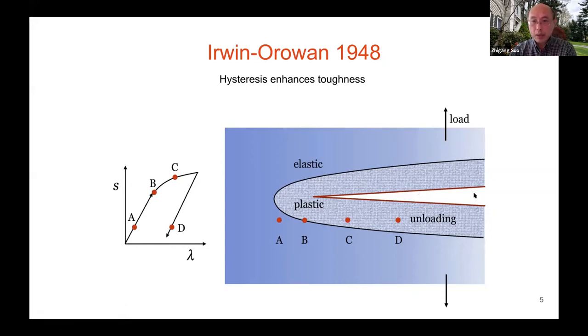If you look at a crack running in such a material, way ahead of the crack you're elastic, you're at A here. And then way behind the crack, you're at D. So as the crack moves forward, a material particle will undergo this hysteresis and dissipate this energy. Now, the point is this zone is macroscopic. It's not atomic scale anymore, typically on the order of millimeters to centimeters for steel. That releases an enormous amount of energy. So all of the fracture mechanics principle has been just an elaboration of this single sentence. Okay, that's good. Today, I will not elaborate on this. It's still an ongoing theme.